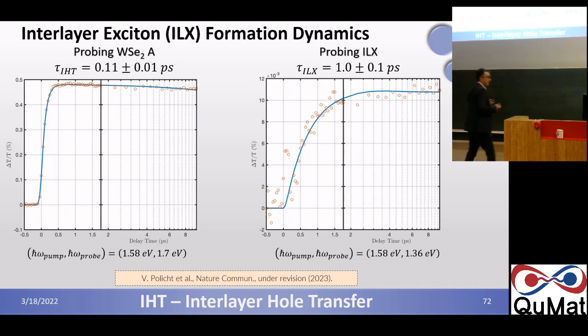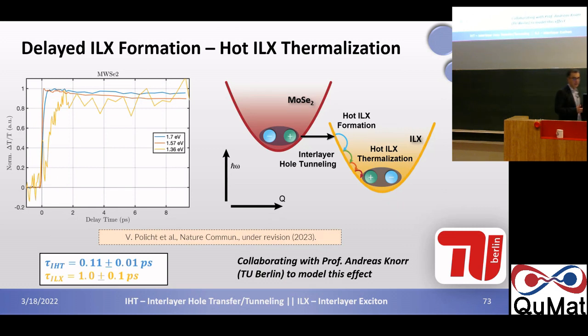picosecond. Again, we asked for the help of the group of Andreas Knorr in Berlin, and they could model our experiment quite well by considering that this interlayer hole tunneling occurs on a 100 femtosecond timescale. Then it leads to a hot interlayer exciton formation. Then this interlayer exciton thermalizes with phonons. And in the end, the species that emits forms within, let's say, 1 picosecond. So we can follow really all the steps of this charge separation and interlayer exciton process.